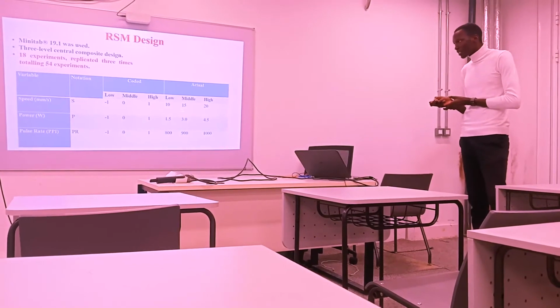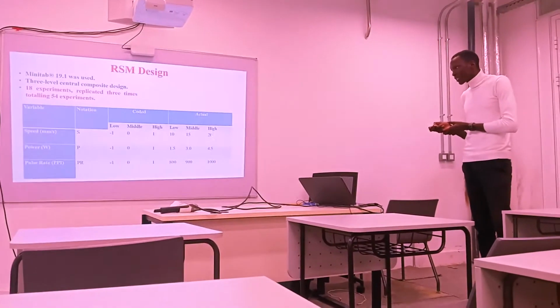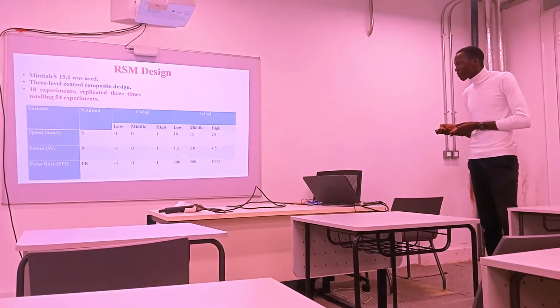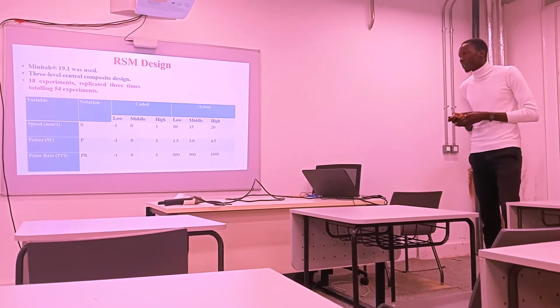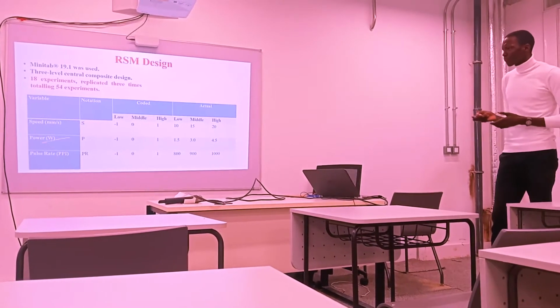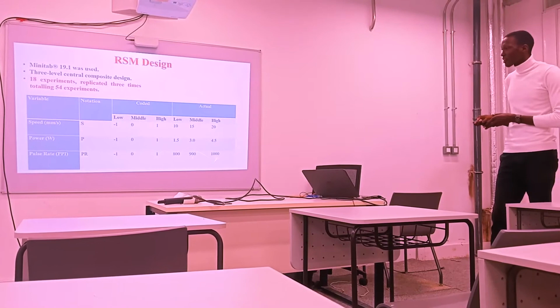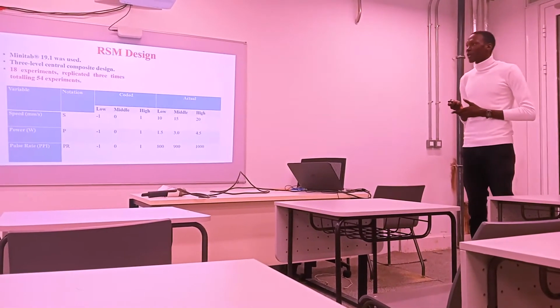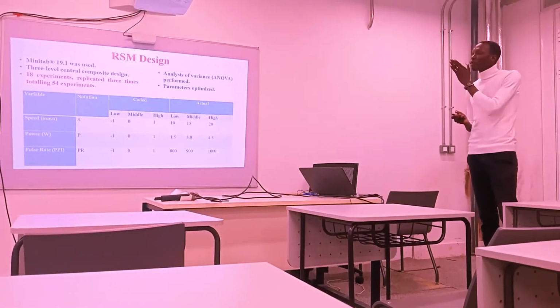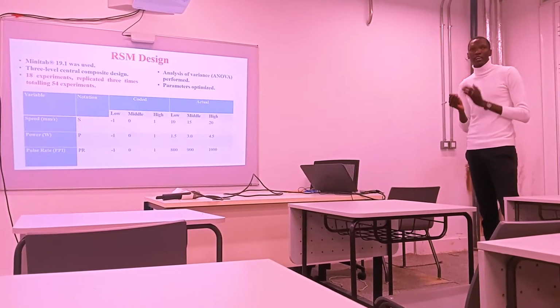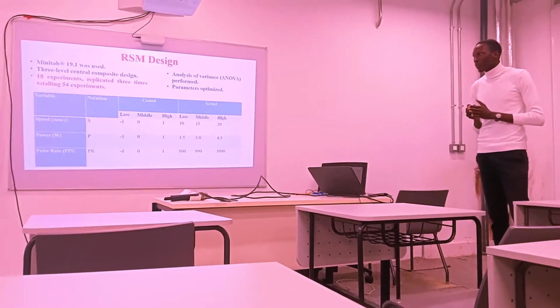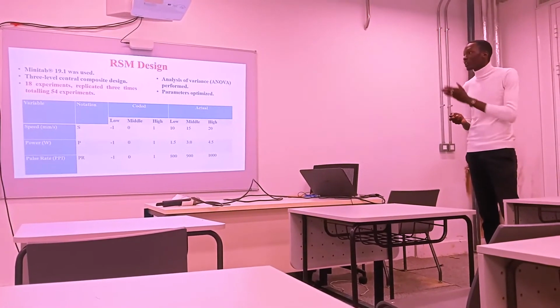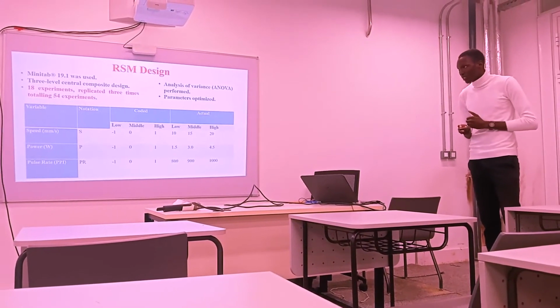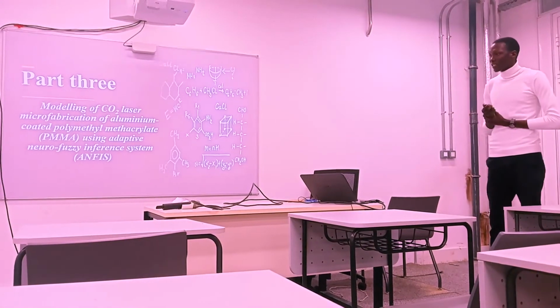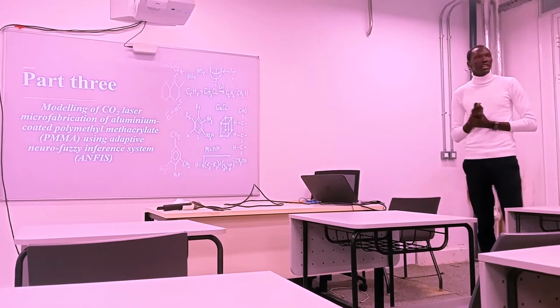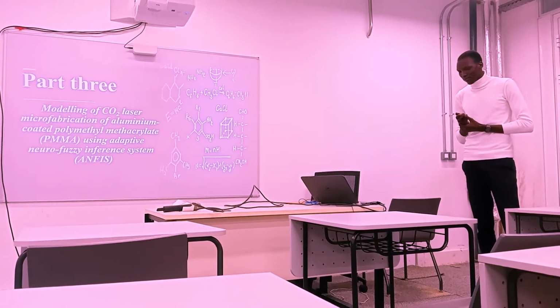We used speed 10, 15, and 20 millimeters per second, power 1.5, 3, and 4.5 watts, and the pulse rate 800, 900, and 1000 pulses per inch. We performed analysis of variance to find out the significance of the inputs on the responses. And then we optimized the parameters. Then in the last part, we modeled the process using adaptive neuro fuzzy inference system.